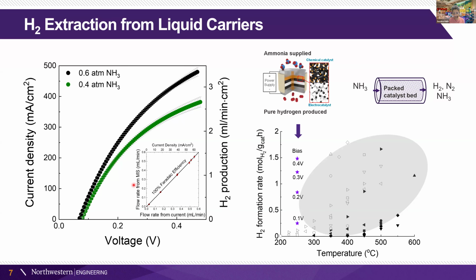This does not mean that it has 100% energy efficiency. It means that for every electron that we deliver, we achieve one hydrogen ion going across our electrolyte, and we have no parasitic reactions. We didn't expect to have any parasitic reactions, but that was a nice confirmation.